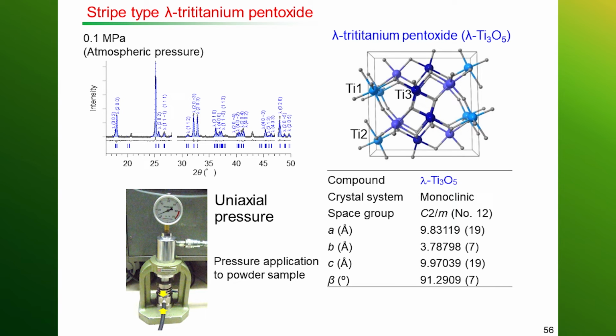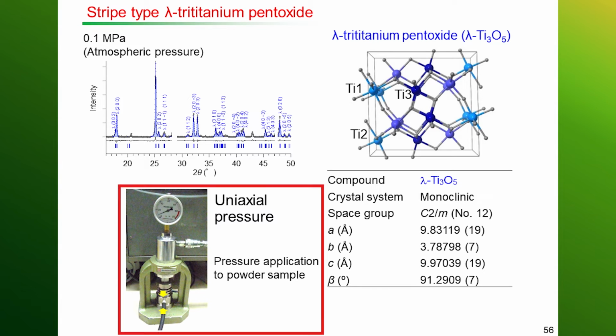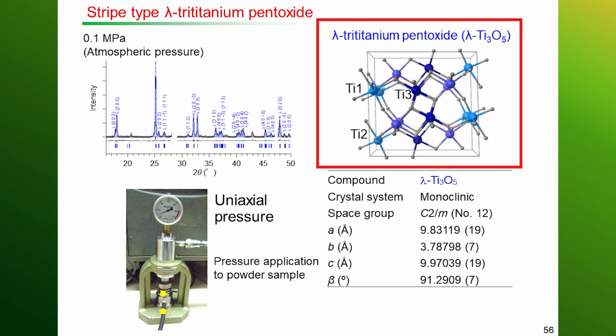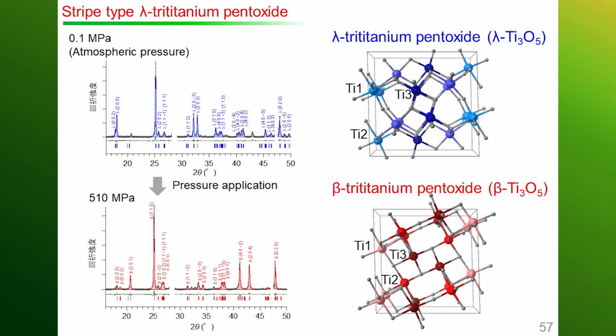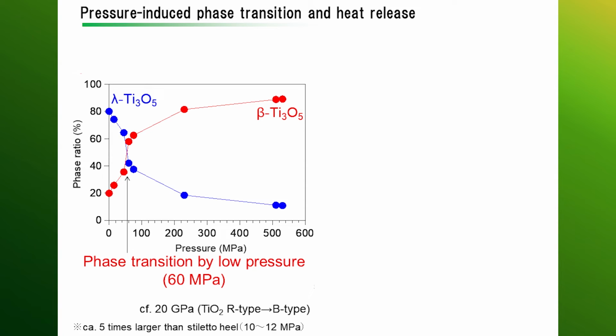What's interesting about this material is it's a black powder, and you cannot measure powder, so we applied pressure to make it into pellets. And under pressure, it changed from the lambda crystalline structure over here to beta, which is well known, and we did this through pressure. We wondered what was happening, and we checked the pressure. And we found that the change from lambda to beta, this is the phase ratio, occurred at 60 megapascals, which is 600 atmospheric pressures.